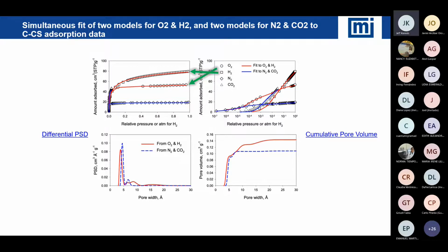And remember when we looked at the fluid density data, hydrogen only has high density in very small pores. So by comparing simply the quantities, we already know this particular material has a very small entrance to the pore. Hydrogen can get in, but it can be very challenging for the others, the nitrogen or the CO2, to enter that pore system. And when we calculate the pore size distribution, notice down below, the use of hydrogen indicates smaller pores than if we were simply using nitrogen or CO2.